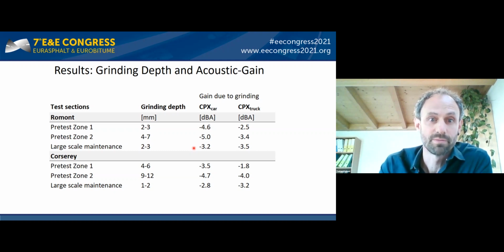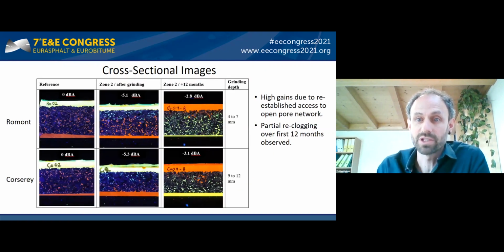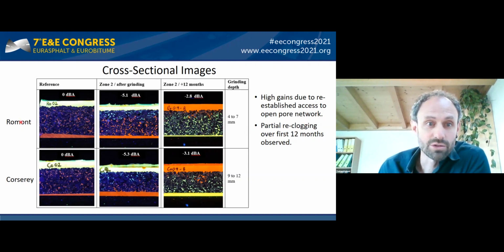To put this in relation, a decrease of 3 decibel is usually equivalent of reduction of about half of the traffic volume. To explain the high gains at increased grinding depth, we now look at a set of cross-sectional images from drill core taken in zone 2 with a grinding depth of 4 to 7 millimeters in Romont and bottom row drill cores at grinding depth 9 to 12 millimeters in Corserey.